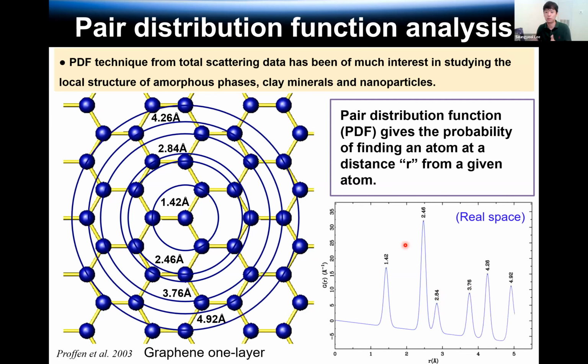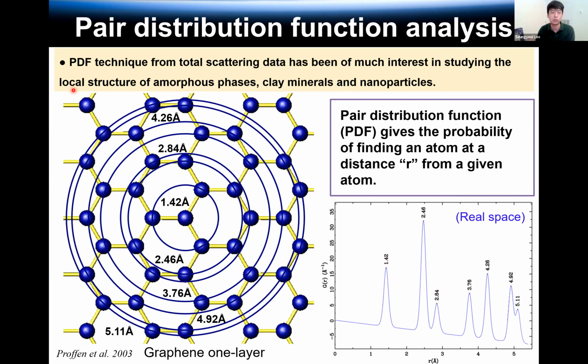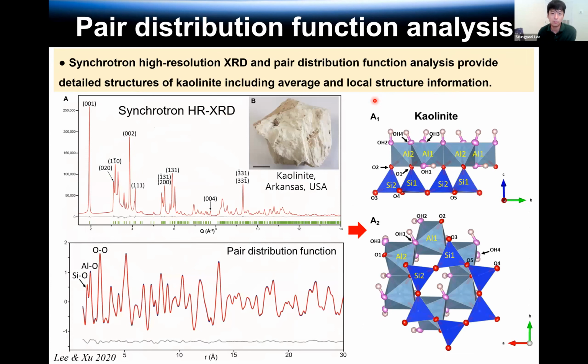So yeah, this method is a very powerful tool. We can directly know the atom to atom distance with this method. People use this method to study local structure, mainly amorphous phases, clay minerals, and nanoparticles. So I applied this method to a kaolinite sample. I analyzed the kaolinite using synchrotron high resolution X-ray diffraction and also the pair distribution function method. And this is the kaolinite structure.